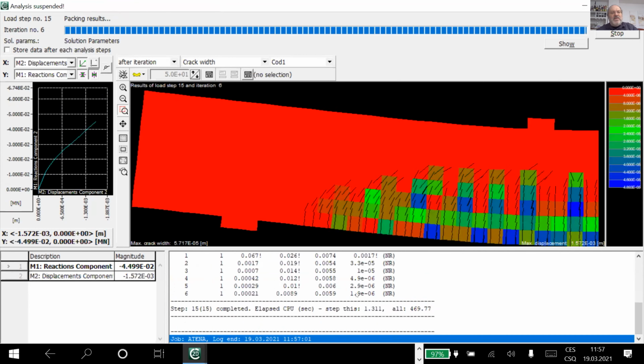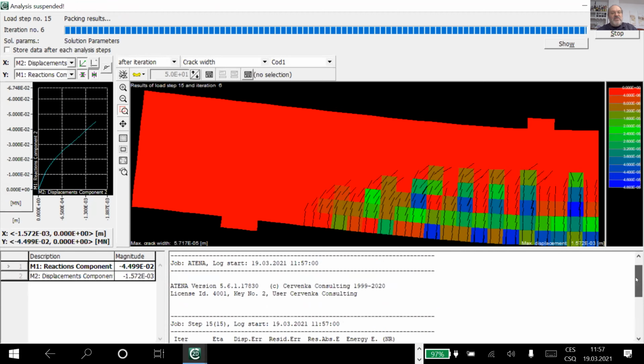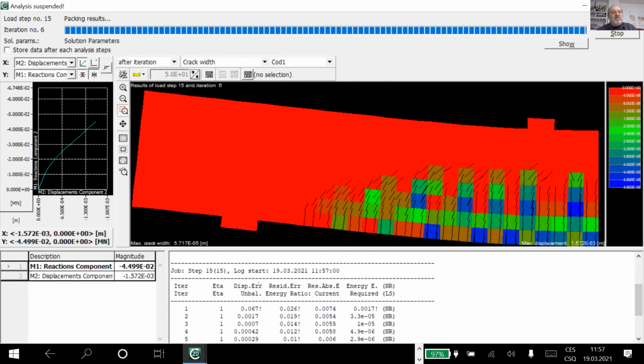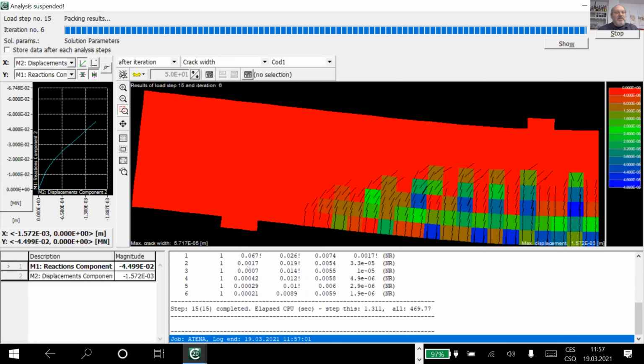Not successful now. So you can see that in the values, this sign means not converged. As soon as we achieve 1% everywhere, it is converged in all columns. The columns represent the particular criteria which we defined in the solution method. So it's the error in displacement, error in residual forces, the absolute maximum residual force, and the energy. And then we have 1% for the first 3 and 1% squared in the last column. And this is the iteration procedure, and you can see that in 6 iterations we are still on the ascending branch, we achieved the equilibrium. Well, and the development of cracks you can see in the main picture.